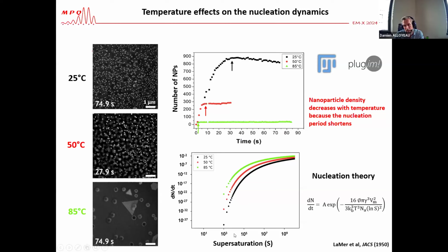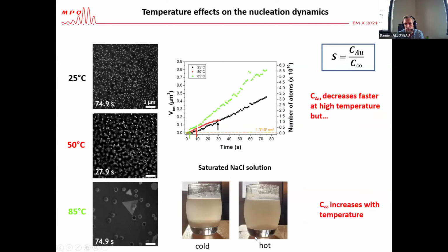So now we have to think about what happens with this parameter, the supersaturation. Supersaturation is in fact the ratio between the concentration of gold precursor in your solution and the equilibrium solubility of your solution. And what is great is that we can quantify the gold precursor concentration in the solution, because it is the same in all the experiments at the beginning. And we can quantify the total amount of gold that we have inside the nanoparticles. And what is inside the nanoparticles is not anymore in the solution. And you see that with the growth, you have more gold inside those few large nanoparticles than in the many nanoparticles that you form at 25 degrees.